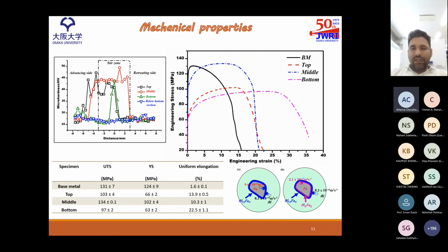And coming to the tensile properties, we can see that the middle section has the highest tensile strength as compared to the bottom and the top one. Now why? Because of the bimodal distribution, the fine grain size provides the strength, whereas the large grain size helps in the dislocation accumulation and thereby provides the higher elongation as compared to the other one.